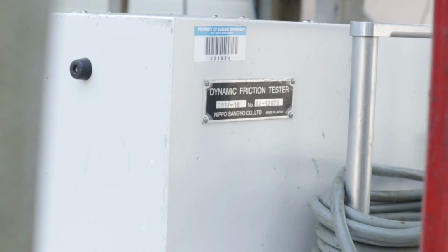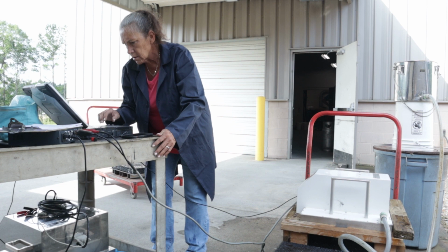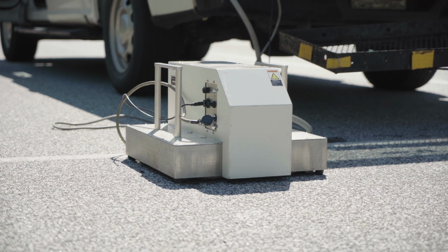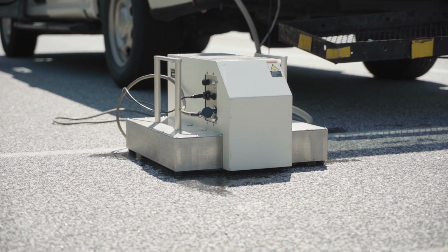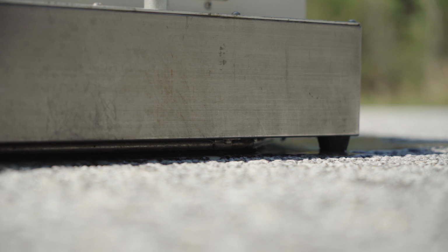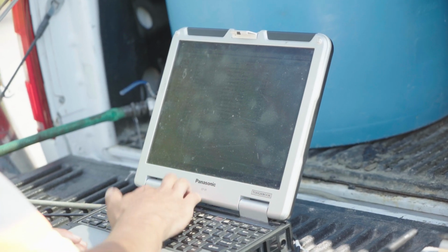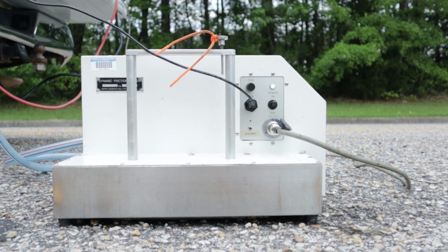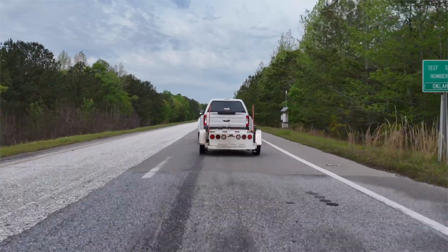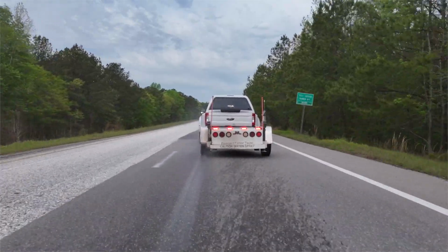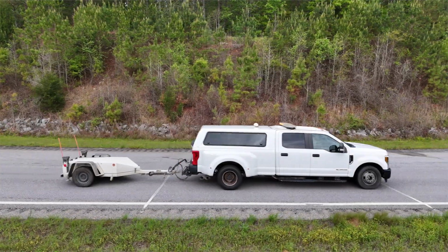We've also done some work in recent years incorporating friction in mix design before sections get placed on the track, where we tried to hit certain friction targets in the lab and then transfer those to the field and see how well laboratory friction results could predict or relate to field friction results. We've had great success doing that, and I feel very confident that there's a future in that for agencies who want to include friction in a mix design specification. One of the many benefits of performing friction testing on the NCAT test track is it allows us to conduct experiments that involve friction without having to put public lives at risk.